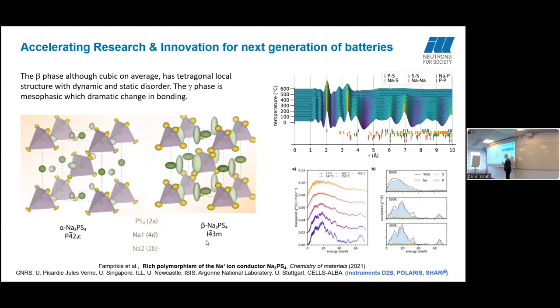But the interesting thing is that at these sulfur and phosphorus positions, there's huge opportunity to actually dope or change into other elements. And that's already started to be explored. This is the phase, the beta phase, that has the highest conductivity. So the exciting thing is the potential to dope this to change the temperature at which you get the transition from alpha to beta. I thought that was quite interesting.